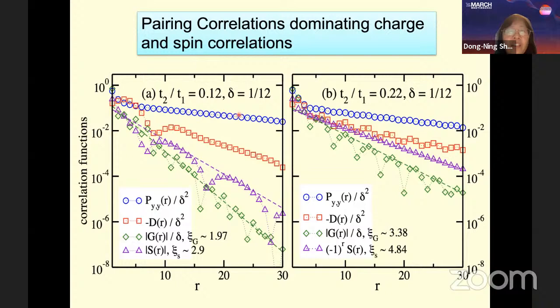Then we can see very clearly at long distance the pairing correlation survives to the longest distance. The second one is density correlation. Following that, the spin correlation also decays—it decays much faster than pairing and density correlation, but slower than single particle electron hopping. Similar behavior is found for the larger T2 over T1.